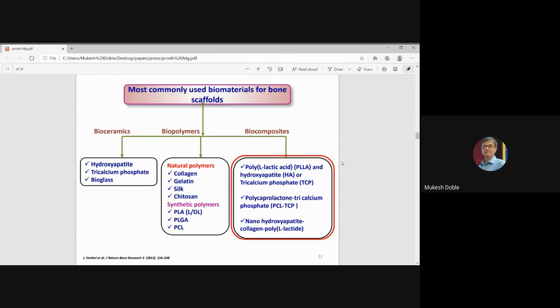Then biocomposites are also used, L-lactic acid and hydroxyapatite, tricalcium phosphate, polycaprolactone, tricalcium phosphate. So these sort of composites, advantage of it is when you use inorganic, most of the inorganics are very biocompatible, like tricalcium phosphate, hydroxyapatite, bioglass. They're all very biocompatible, and polymers can be the base material or the parent material. So together, you get a lot of properties. Of course, load bearing is much lower, but with polymer present, load bearing can be improved. So these composites are also used quite a lot in biomaterials for bone scaffolds, bone implants, fillers, and so on actually.